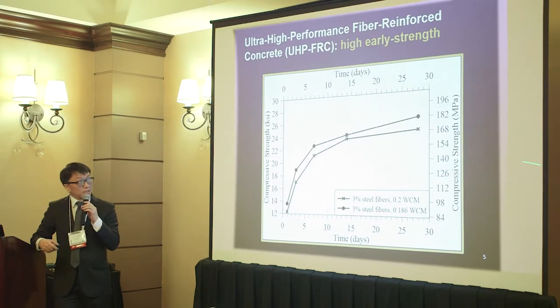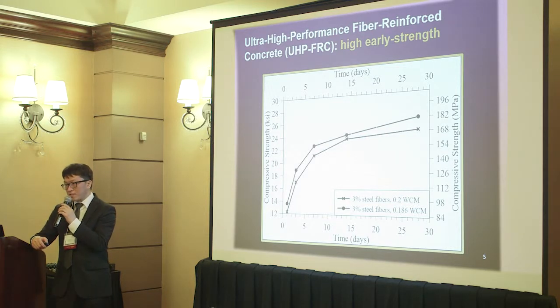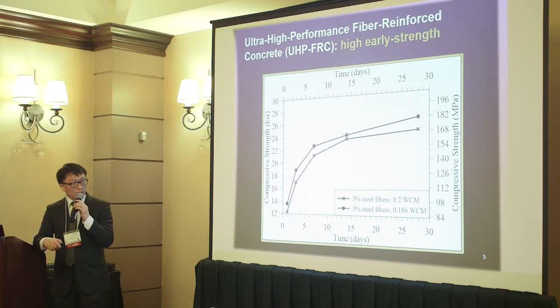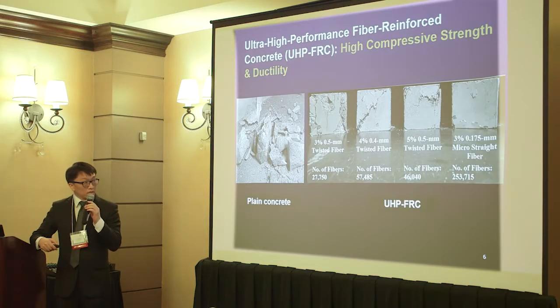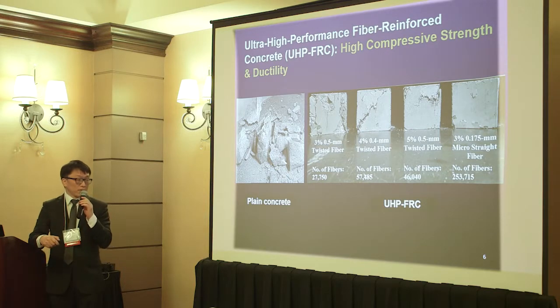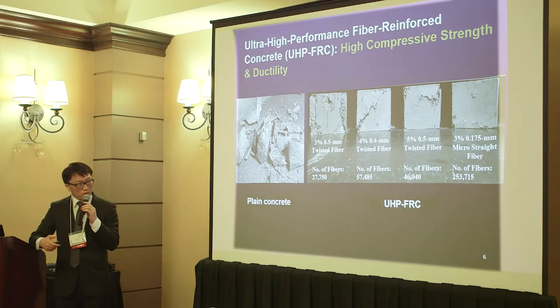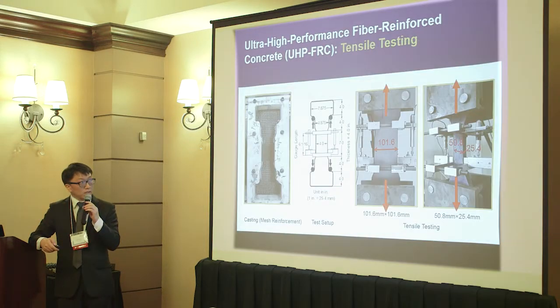This is the one we developed at UT Arlington about 5-6 years ago. We keep improving that. And the early strength is very high. In one day it can reach about 10 to 14 KSI. Long term it can reach ultimately 30 KSI. You can see its compressive property is high. Also, not only the strength but also ductility. Compared to plain concrete, it's very ductile. It's very hard to be crushed compared to conventional concrete.